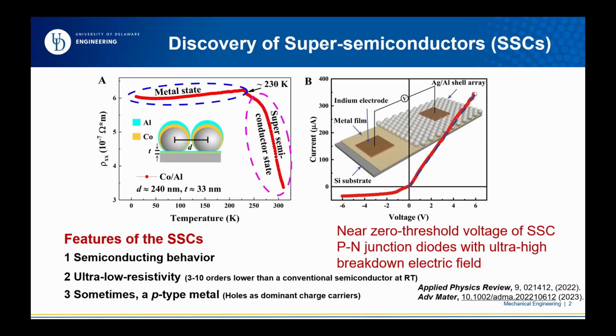Since this resistivity drop is by almost 1 order of magnitude, we call this a super semiconductor, because it shows semiconductor behavior and at the same time very, very high conductivity. How high is that? If you simply compare with traditional silicon, a typical semiconductor, intrinsic silicon without any doping, the conductivity should be 10 orders higher than this intrinsic silicon. Even compared to heavily doped silicon, we still have 1,000 times higher conductivity.